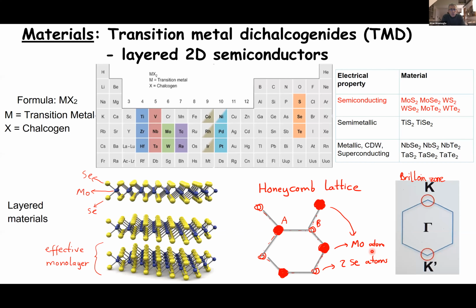So very briefly, transition metal dichalcogenides are actually not all semiconductors. They form a sizable subgroup of more than 5,000 layered materials that we know. The ones that are of interest for this talk are the semiconducting ones, and particularly molybdenum diselenide is what we use in practically all of our experiments. What I refer to as a monolayer TMD is actually a tri-layer structure where a triangular lattice of molybdenum atoms is sandwiched in between two selenium lattices. If you look at it from a distance, we have an effective honeycomb lattice where the A site is occupied by a molybdenum atom and the B site is occupied by two selenium atoms.